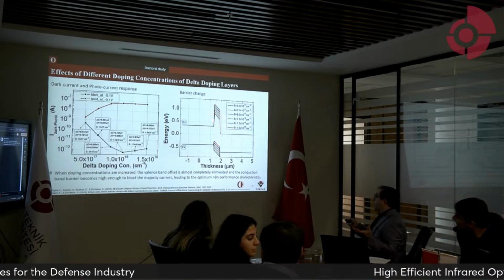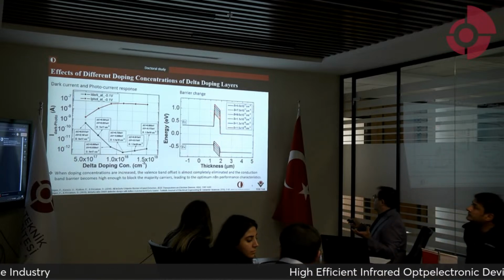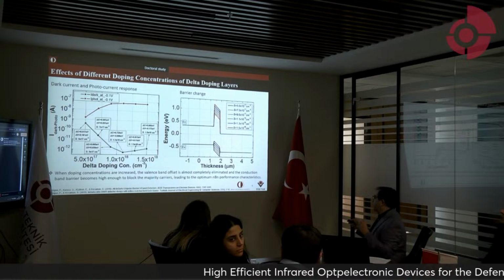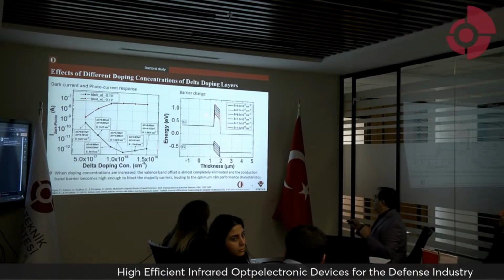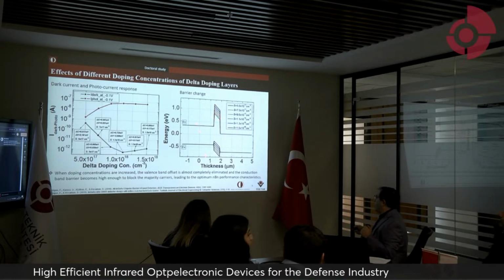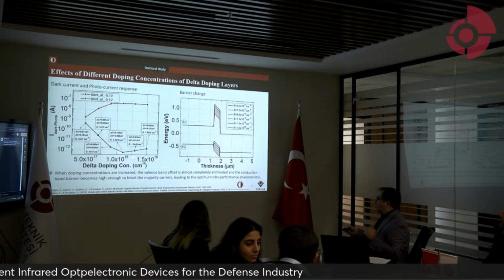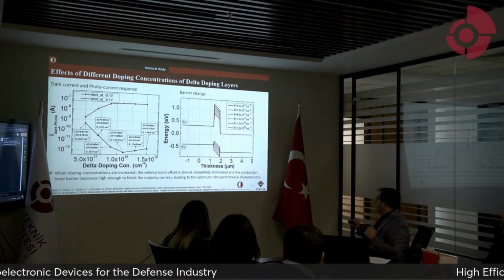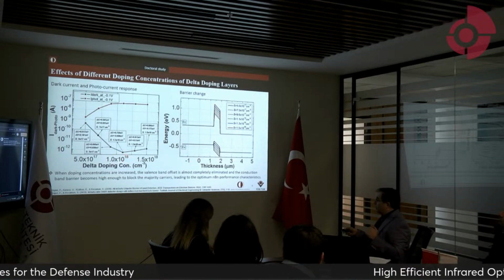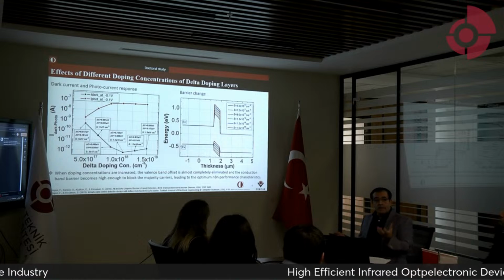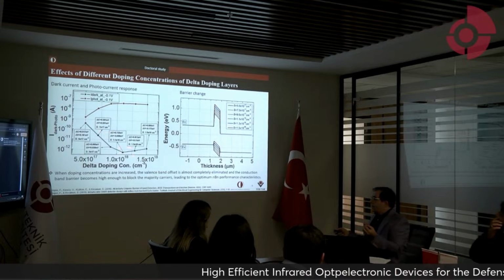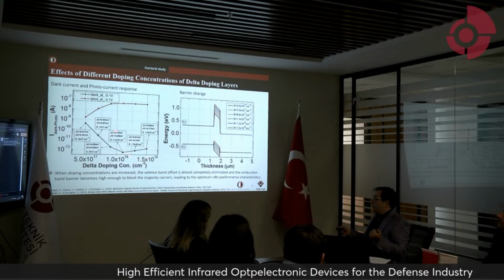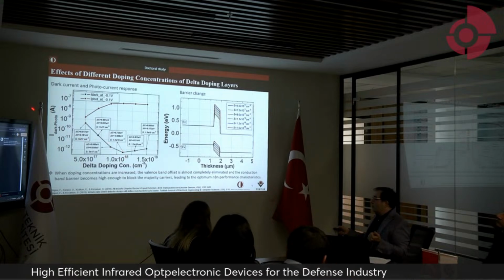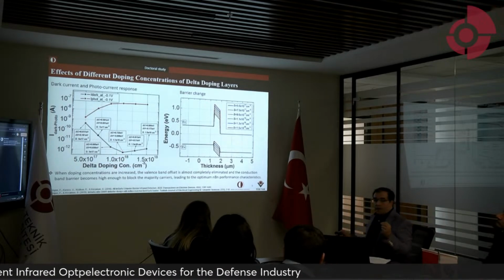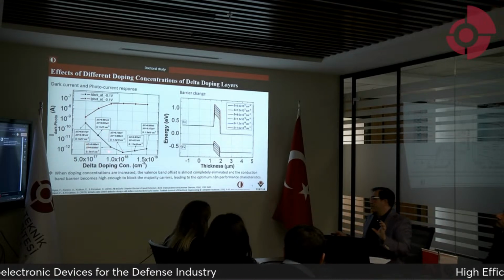Our conduction band barrier is high enough to block the majority carriers, so we need an optimum for performance. If you increase the doping too much, the electric field also increases the dark current, and because of this simulation, you can find an optimum concentration.